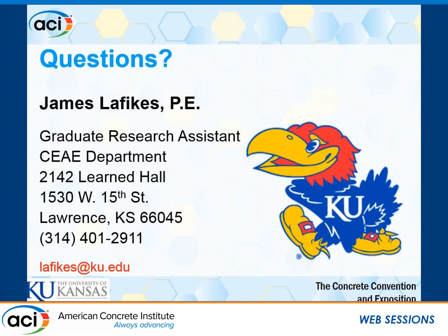Did you look along the bar level to see how the chloride distribution varied with time? Because I know I've seen with 3/4 inch aggregate and 1 inch cover, at the 1-inch level, the chloride is not uniform by any means. Not for the settlement cracking specimens. On the corrosion specimen by itself, when those specimens initiate, we will drill into the side of the specimens at the level of the reinforcing bar and then examine the chloride concentrations at those. Great. Thank you very much.